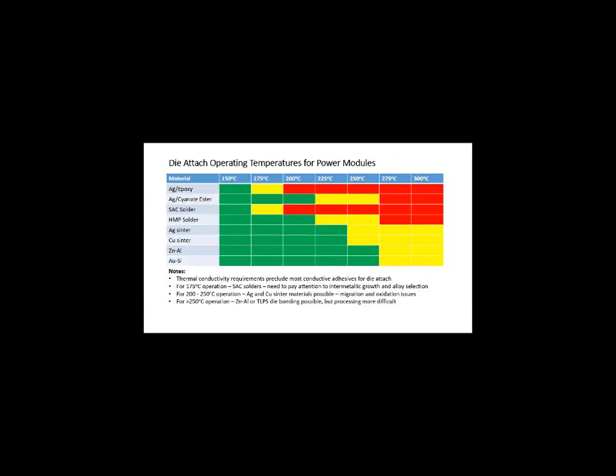So if we look back at the chart, which I call die attach for power modules, and see what's available, what we can see is that the thermal conductivity requirements preclude most conductive adhesives for die attach for getting power out of devices. If you're looking towards something like 175 degrees C operation, SAC solders are theoretically okay to be used, but as you push the temperature or the thermal cycling, you really need to pay attention to things like intermetallic growth and alloy selection.